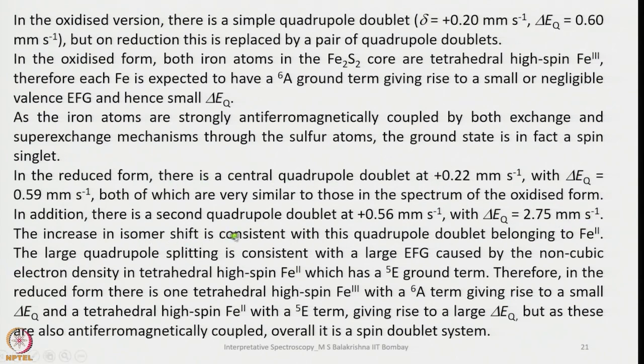The increase in the isomer shift is consistent with this quadrupole doublet belonging to iron 2. The large quadrupole splitting is consistent with a large EFG caused by the non-cubic electron density in tetrahedral high spin iron 2, which has a 5E ground term. Therefore, in the reduced form, there is one tetrahedral high spin iron 3 with a 6A term, giving rise to a small ΔEQ, and a tetrahedral high spin Fe2+ with a 5E term, giving rise to a large ΔEQ value. But as these are also antiferromagnetically coupled, overall it is a spin doublet system. This is how the data is interpreted.